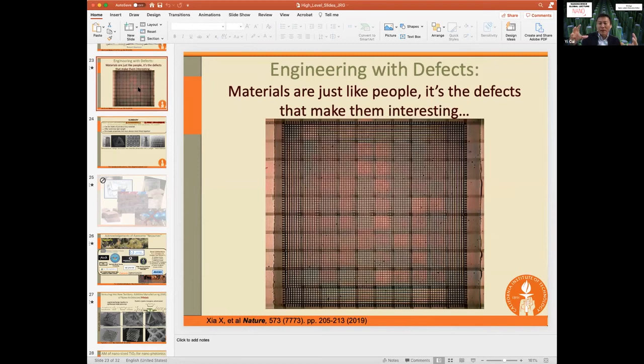You have the 3D metal materials architecture. When you press on it, certainly globally you are seeing this deformation, but locally there's a lot of bending motion, right? And the size effect, the thickness, roughly about 10 nanometers and below, you start to see something dramatic on the wall thickness. So can you educate us a little bit, if you think about locally, what's the nature of deformation right there? And are you really stretching the chemical bond or compressing the chemical bond, or are you translating this into a bending motion? How do people think about this?